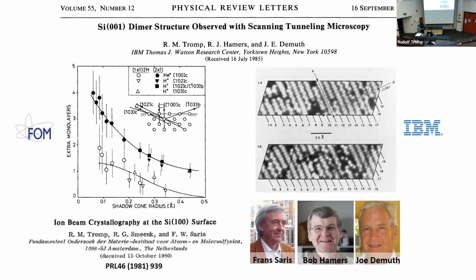microscopy. So we looked with STM together with Bob Hamers and Joe Demuth at this silicon 100 surface, and we saw these little jelly beans. You see these rows of jelly beans? They are dimers. And this was the first time that anybody had ever seen atoms on this silicon surface and understood in real space what the structure of this surface is. Plus that there's a lot of defects in the surface, but that's typical for surfaces, right? There tend to be a fairly large number of defects.